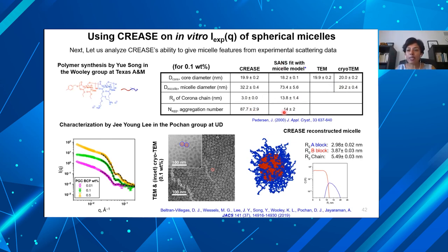The reason probably the analytical model didn't do super well is these are very complex polysaccharide backbones, charged side groups. Likely the analytical model was not taking the statistics of the chain conformations right, and thus over-predicting some of the micelle diameter. And that's why it failed. And that's why CREASE is a good method to work with.